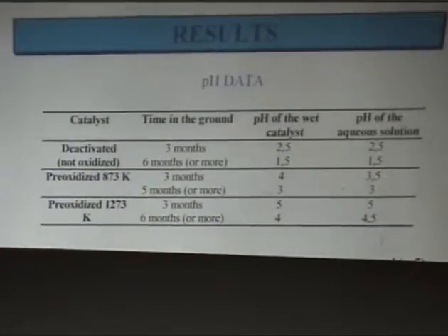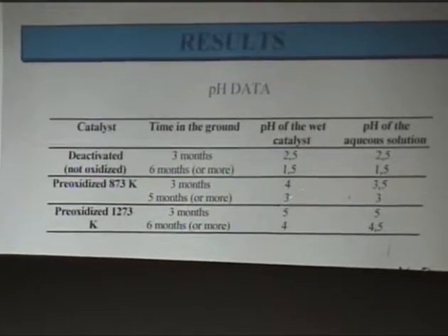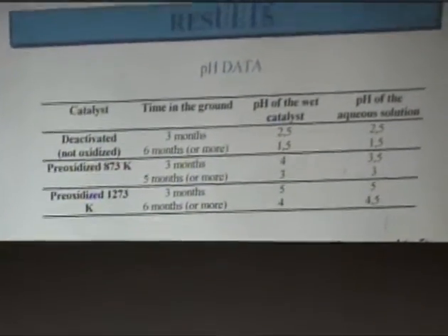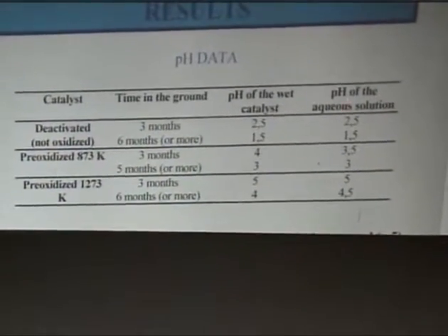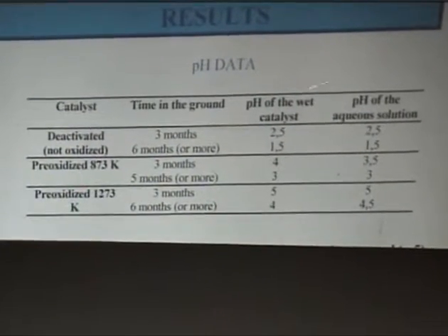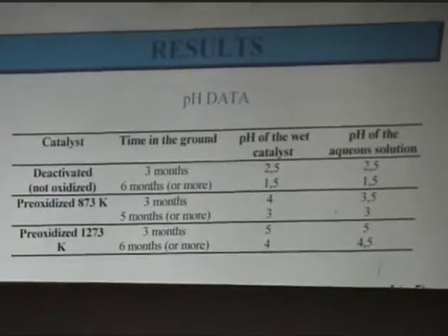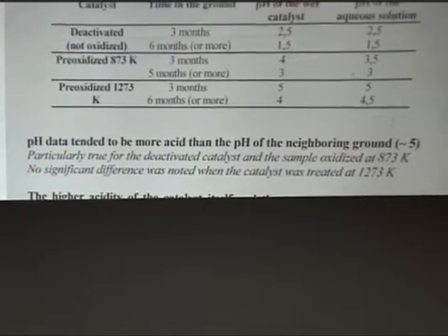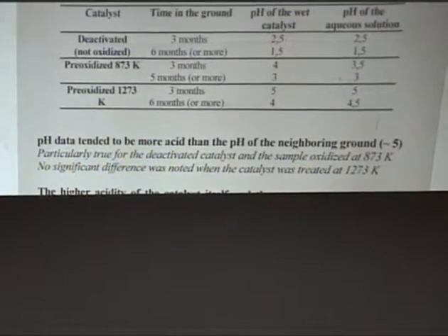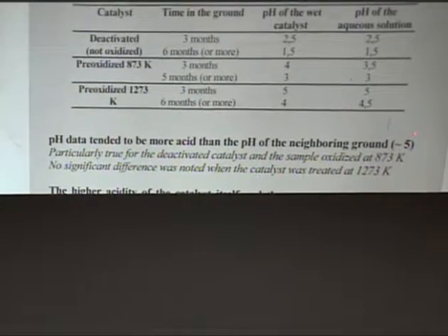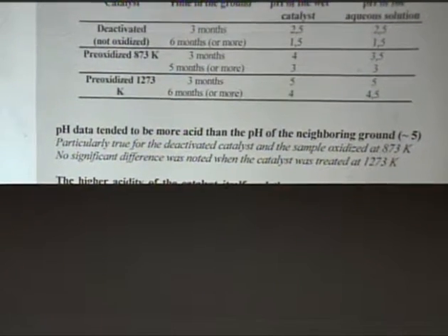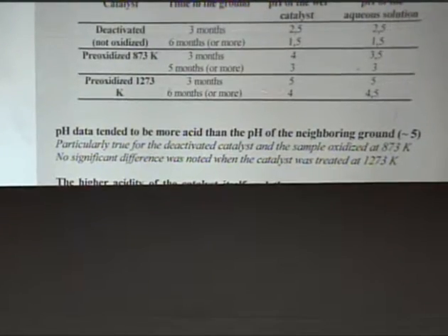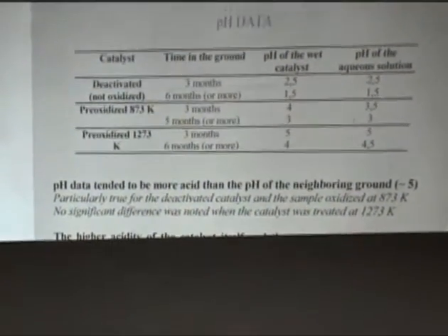The pH data of the catalyst itself and also of the aqueous extract obtained after the Soxhlet procedure showed that they are always acidic. However, the acidity decreases as the temperature of preoxidation increases for both cases. And in general, the pH of the wet catalyst and the aqueous solution are more acidic than the neighboring ground, more or less pH 5, except for the catalyst treated at very high temperature, where the pH data didn't show any significant difference.